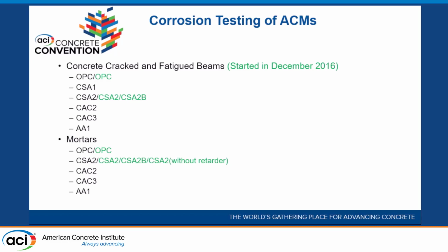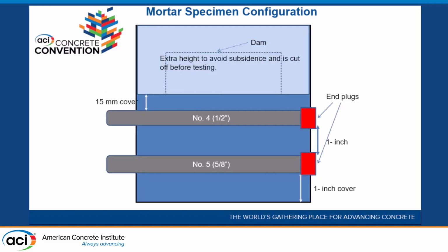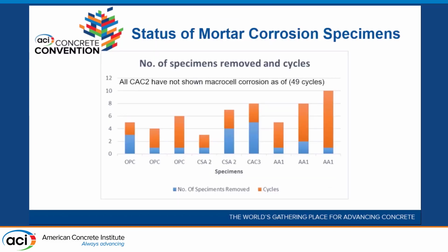So for the corrosion testing, we had a whole list of things. We looked at both concrete, cracked, and fatigue beams. We also did some testing in mortars. The mortar testing was a simple test where we had a small bar on the top, a larger bar on the bottom, and we ponded them with chlorides. These samples were never stuck in lime water. They're all fog room cured, so they're not affecting anything in there. We ran those tests for various periods of time, and we moved them when we had corrosion occurring in OPC. In this particular series, OPC did not do as well as some of the other things, but AA1 did well.